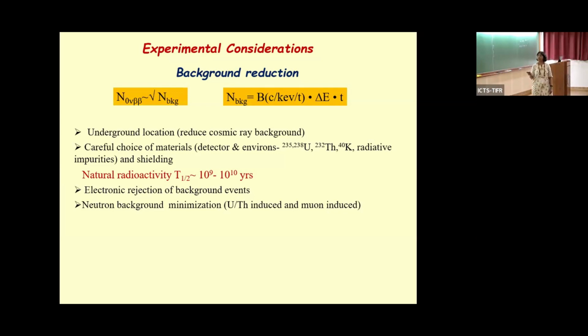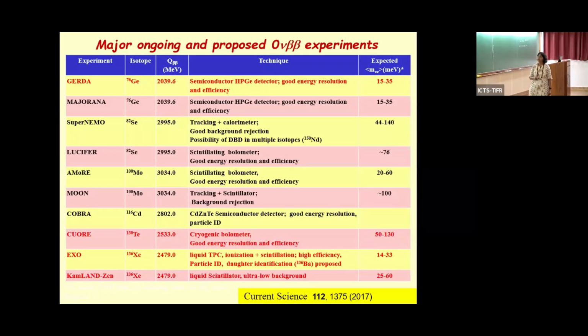So where do the neutrons come from? All the muons, as they pass through various materials, generate neutrons, and they're fast neutrons, but they travel through various materials and will slow down. And uranium and thorium, whatever trace elements they are, undergo fission and they also have alpha decay. So these alphas which come from uranium and thorium also make reactions on light elements like silicon, magnesium, sodium, which are around, and then generate neutrons, and fission of course generates neutrons. So those are the things which you have to really take care of.